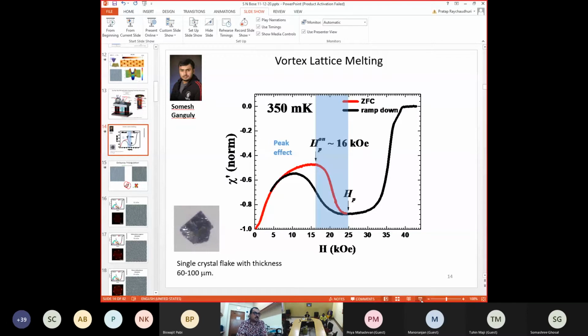So this is our crystal. This is a typical crystal, rather we have many crystals of this kind. We took a plate which is about 60 to 100 micrometers, so it's a thin plate, and we decided to look at how the vortex lattice evolves in this crystal. Before we started, we did the measurement of AC susceptibility, and we observed that there should be an order to disorder transition between the 16 kOe state and the 25 kOe state. But we wanted to see how the disordering actually proceeds.